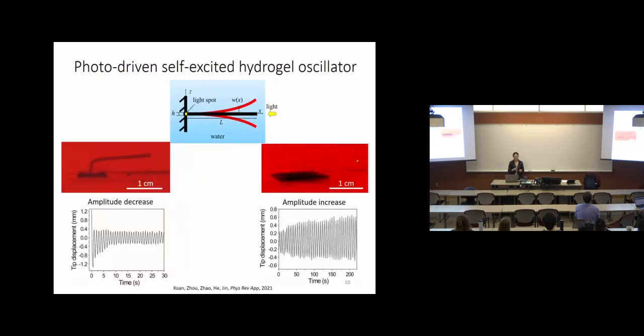Here we are interested in a type of photoresponsive hydrogel, which means when you shine light, there are nanoparticles in the gel which can absorb light and convert it to heat. Then the heat can change the hydrophobicity of the hydrogel, make it hydrophobic, and expel water out of it. So if I shine light locally at some location of the hydrogel, I can create a temperature gradient, and the water can diffuse out, but it takes time. Therefore, it can also create some gradient of concentration within the hydrogel.